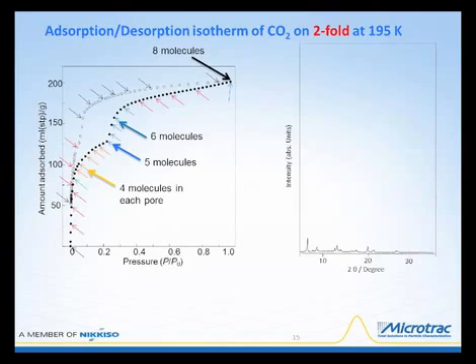But using this integrated system of adsorption, desorption, and XRD, we can follow what's happening along this entire adsorption process. And you'll notice this is a two-step process. And so right away there's some indication that there's some major structural changes occurring, as I mentioned before. But down here at this very first point, I have a representation of the XRD. And please take note of some of these peaks.